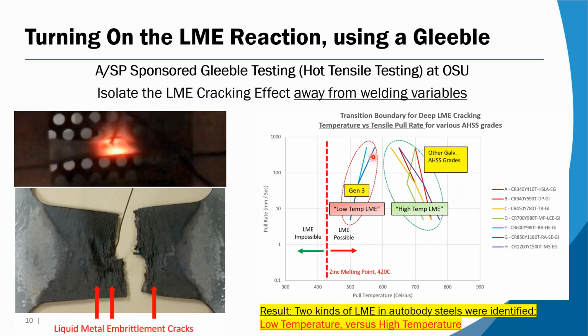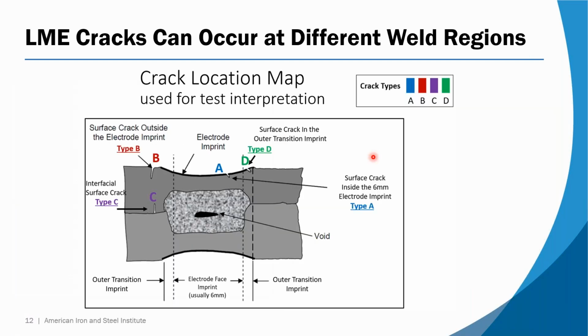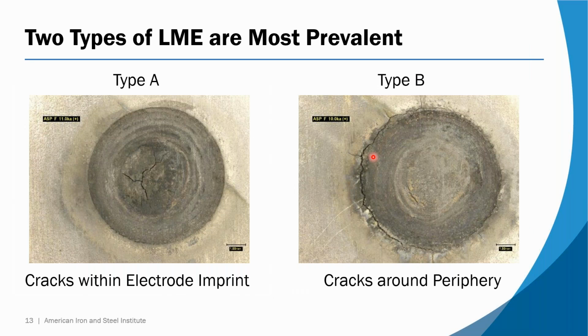When you take this result and you apply it to spot welding, now you have to think about whether you created the same conditions to make this type B crack in a thin sheet or a thick sheet. It's going to affect it. But if you hit that same point that the Gleeble test is predicting the initiation of LME, I think that initiation point is not dependent on the thickness. It's just a matter of whether your weld parameters simulated that Gleeble test condition.